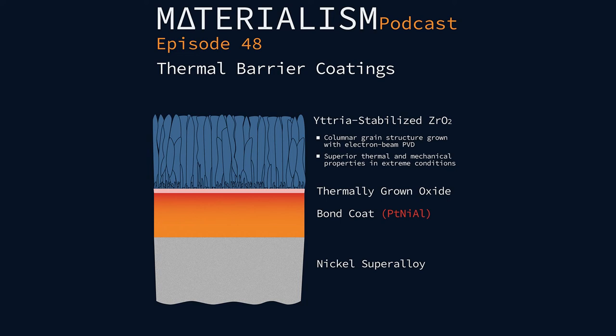But more importantly, if there's this constant volume change, because remember, these things get cycled all the time. They're going high temperature, low, high, low, high, low, high, low. You would be constantly switching the volume of these individual components. And that would cause cracking. It would eventually just break right off, right? So they actually have to avoid that, which is sort of ironic that they're actually trying to avoid what normally is the biggest selling point for YSZ here.